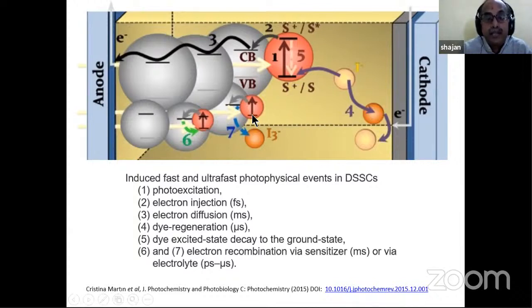Or the excited electron from the dye has not acquired sufficient energy to reach the conduction band, so it can come back to its original ground state. And another process is happening here, that is the regeneration. So all these processes are happening at the same moment: photoexcitation, electron injection, electron diffusion, dye regeneration, and electron recombination. Almost 7 photophysical events are happening in dye-sensitized solar cells.